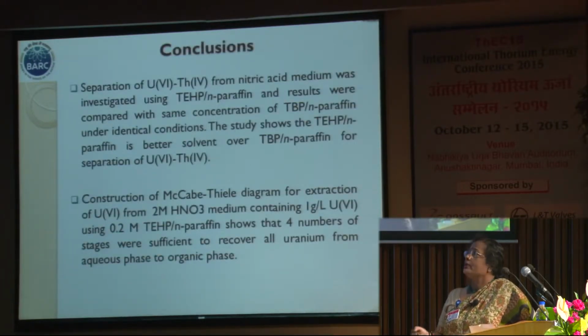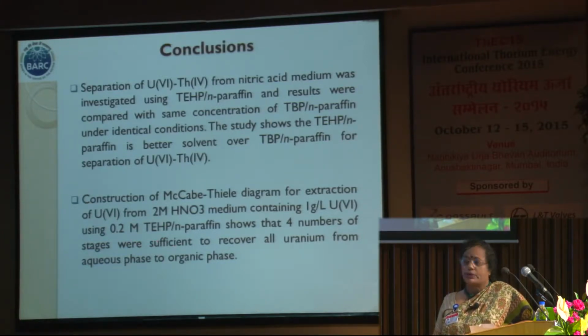So, conclusion: the separation of uranium and thorium from nitric acid medium was investigated using TEHP/n-paraffin, and we could get a good separation. Construction of the McCabe-Thiele diagram shows that within a reasonable number of stages, we are able to extract and strip it back from the system, which is a requirement for production level.